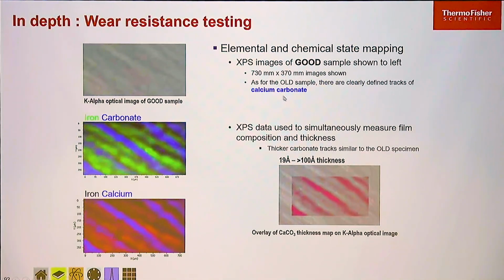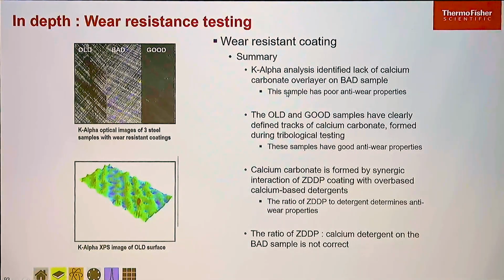If we look at the good sample, we can see again the calcium carbonate, and it's a little bit thicker here, going from about 20 angstroms up to 100 angstroms, and again we can see the distribution of the calcium carbonate. So iron should be red, I think, and calcium's blue, and green and blue here, and again clearly defined tracks of calcium carbonate. On the bad one, we just don't see any calcium carbonate, and the mapping experiment's a complete waste of time. And so that's what it is.